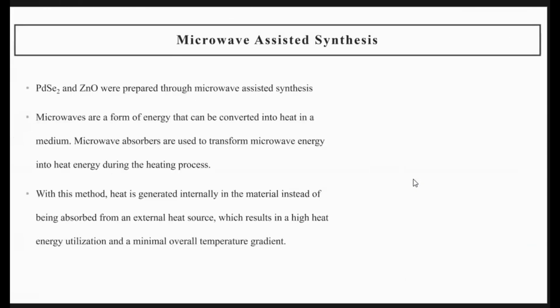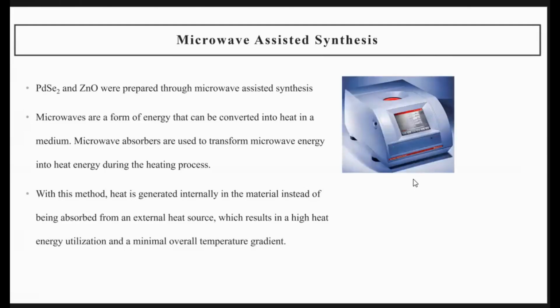A very interesting technique we use for the synthesis of palladium selenide and zinc oxide is the microwave assisted technique, which means here we did not use any CVD or a high level technique. We use this microwave assisted synthesis, which means we are using microwave radiation to heat the sample. We use a solvent for heating the sample.